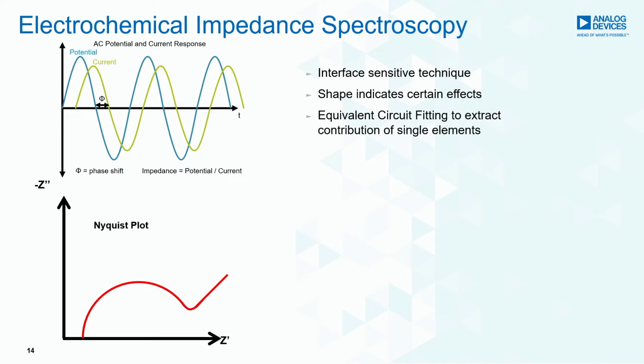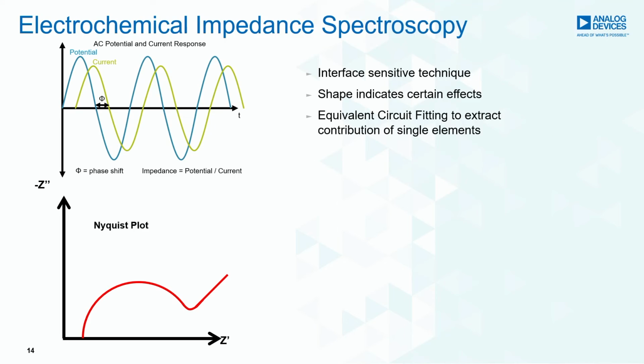With equivalent circuit fitting, that means you take your real chemistry system and think for each of the components of it that give a contribution to the impedance, you think for each of them of an electronic component replacement. So that is what you want to do. You want to replace each of them with an electronic component that you understand. Then you simulate the impedance spectrum of that circuit and try to adjust the parameter that fits. And this way you can extract the contribution of single elements.